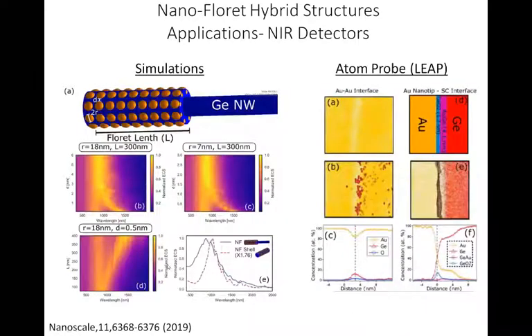We also modeled the optical response of this tip, and we could account for the long wavelength absorbance in the near IR, which depends on the exact interfacial structure of the clusters, which is not just metal-to-metal interaction, but there is the electric layer, very thin, between them. And this long wavelength response is owing to the collective response of this as an ensemble.